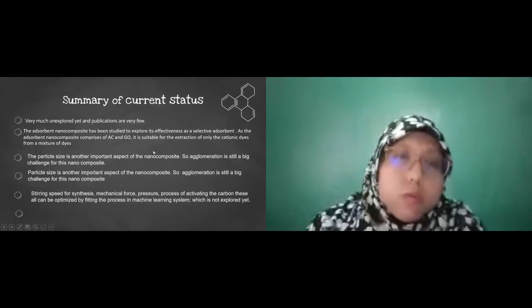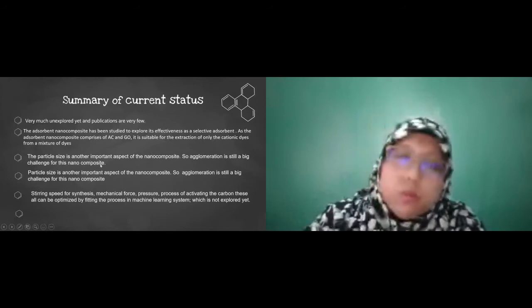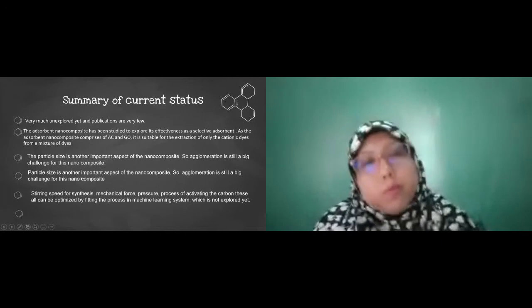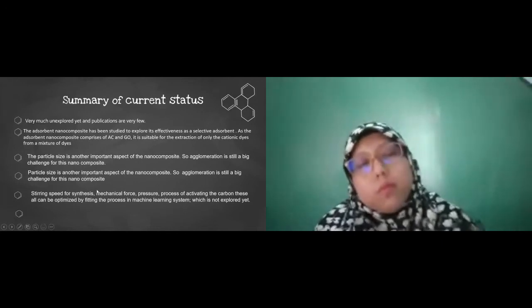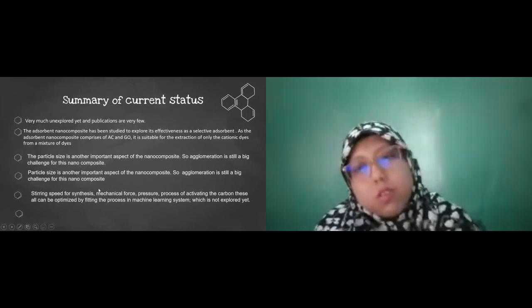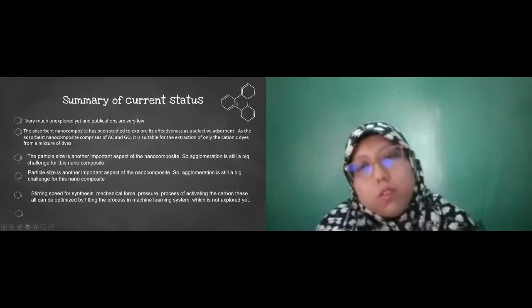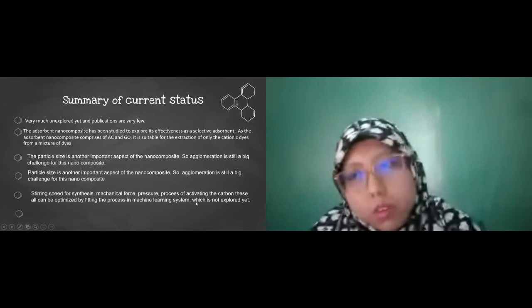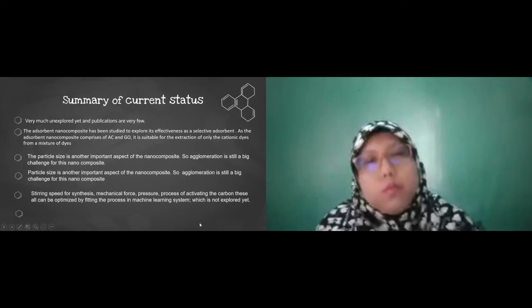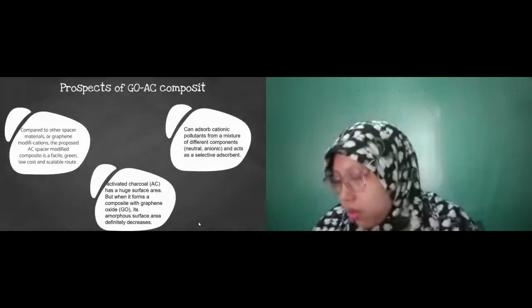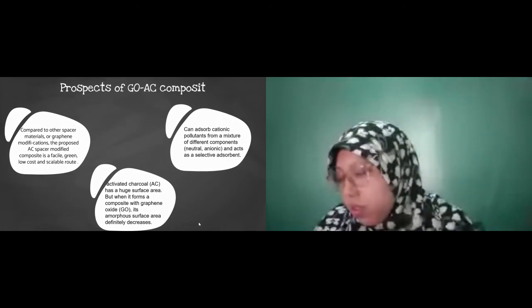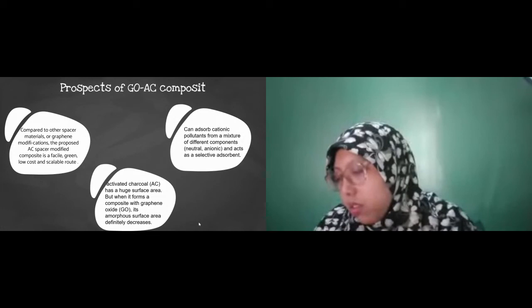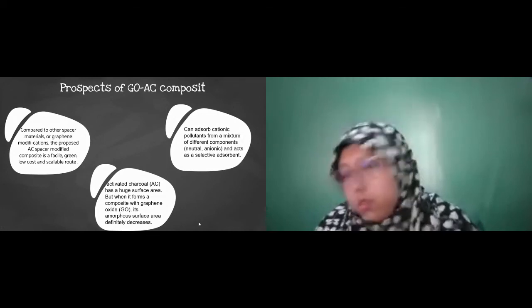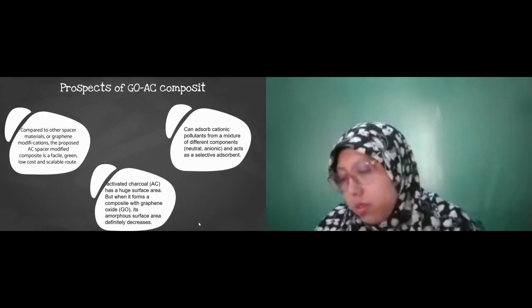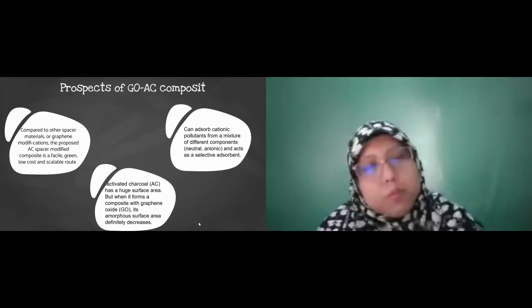So the current status is, I have found very little literature on this, and they are facing many problems, like the particle size, which they cannot control, and agglomeration happening because of the nano size. Temperature also matters there: if temperature is high, the agglomeration goes higher. Stirring speed, mechanical force, pressure, and the process of activating the carbon all contribute to the composite. So all these can be optimized by machine learning, and I see very good prospects for it. Compared to all other spacer materials, graphene is a very good spacer, and if activated carbon is used with graphene, then compared to graphene metal oxide or graphene polymer, this is a facile, green, low-cost, and scalable route.